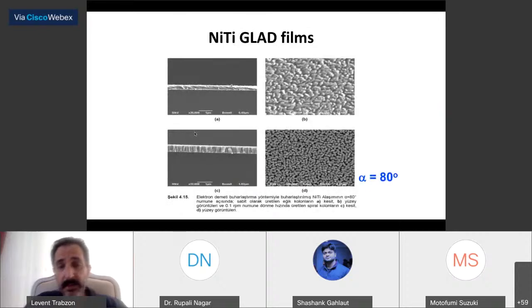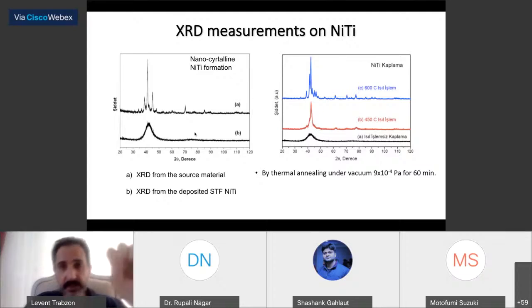And we also studied nitinol GLAD films. These are some examples. We also measured XRD data on the nitinol GLAD films. When you deposit nitinol GLAD films, they are non-crystalline. But after you thermally anneal them under vacuum, you get very nice crystalline nitinol films.